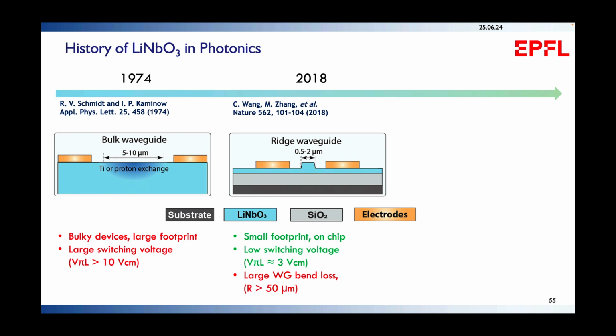That has been developed by Sohler in Paderborn in Germany. There's been a Chinese company that has used this technology called NanoLN. And NanoLN has made smart-cut, so ion-sliced, lithium niobate on insulator commercially available. Very shortly after that commercial availability, the first results came out from Harvard, from my colleague Marco Loncar, showing that you can make modulators out of this material that have switching voltages that are CMOS compatible with bandwidth that can reach 100 gigahertz.